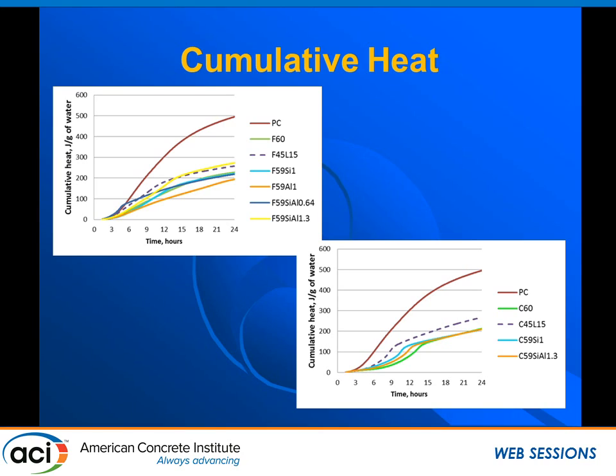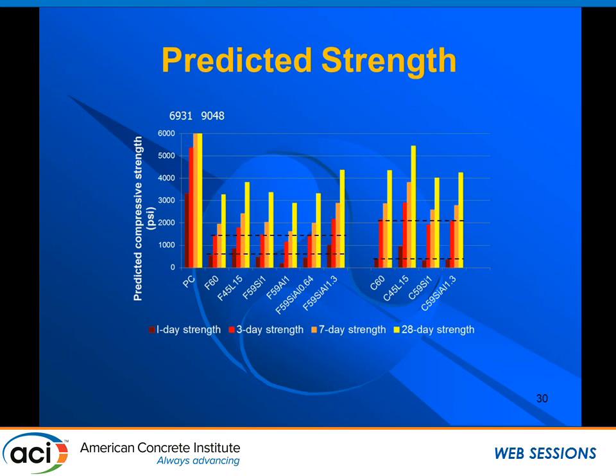In this case, we increased with 1.3 and with 0.64. Here we didn't increase with anything. We predicted the strength, and our main objective is to improve the early strength. It appears that, again, limestone improves the strength both at early age and later age, and we confirmed that with measuring.